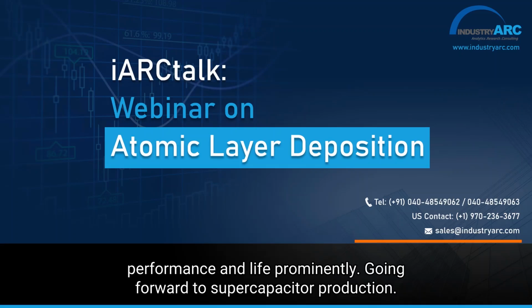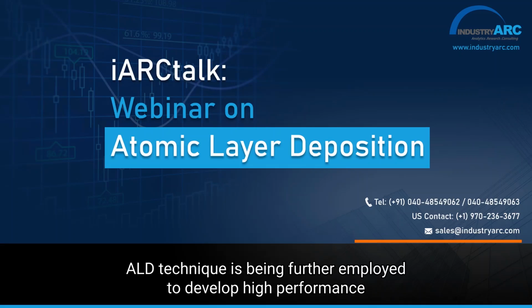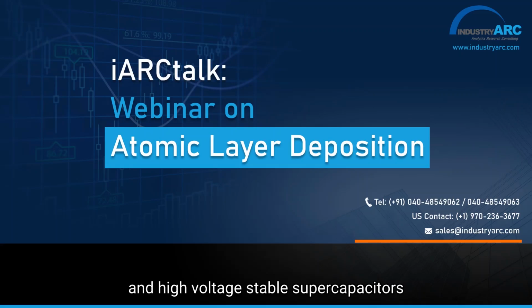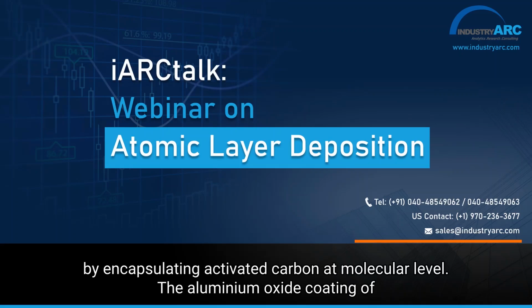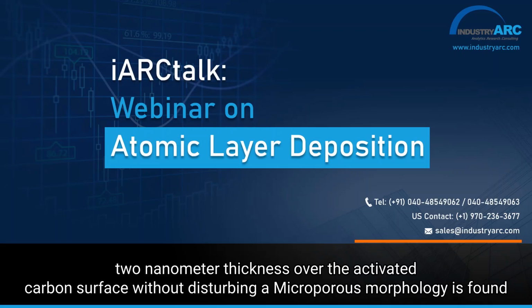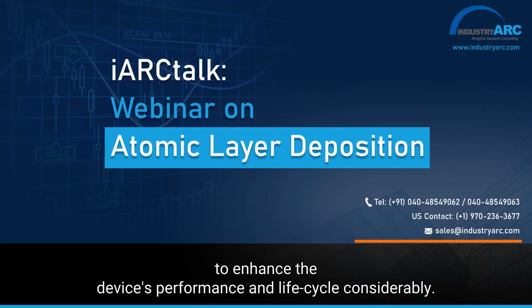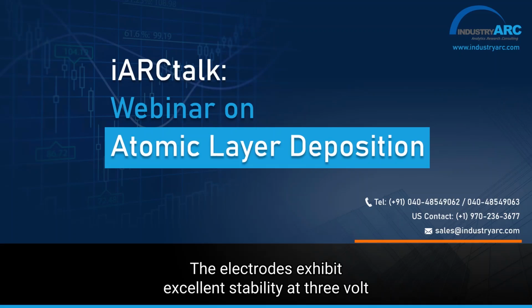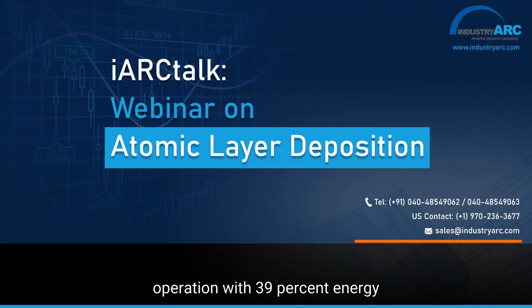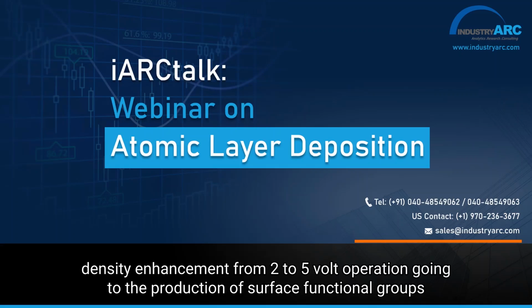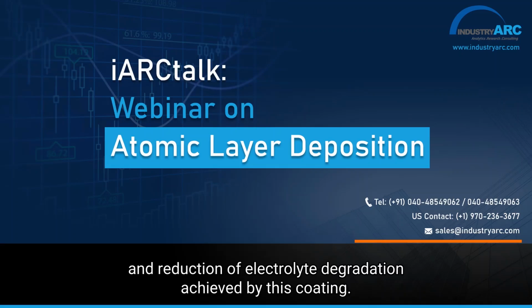Going forward to supercapacitor production, the ALD technique is being further employed to develop high performance and high voltage stable supercapacitors by encapsulating activated carbon at molecular level. The aluminium oxide coating of 2 nanometer thickness over the activated carbon surface without disturbing its microporous morphology is found to enhance the device's performance and life cycle considerably. The electrodes exhibit excellent stability at 3 volt operation with 39% energy density enhancement from 2 to 5 volt operation owing to the production of surface functional groups and reduction of electrolyte degradation achieved by this coating.